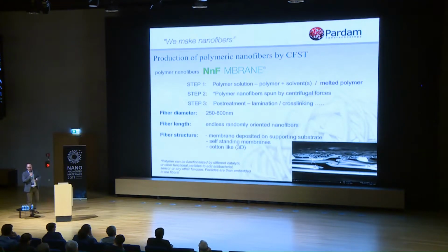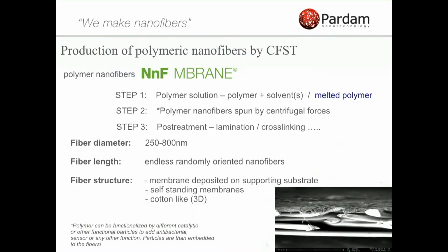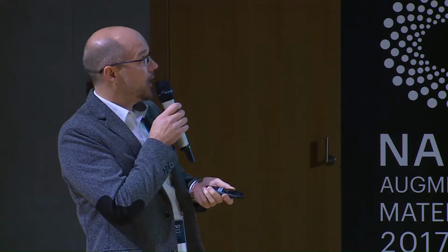It's a little bit easier to make polymeric nanofibers. You basically have, again, polymer solution, which you prepare by dissolving polymer in solvent or in combination of solvents, because the creation process for nanofibers is based on evaporation. So we sometimes combine 2 or 3 different solvents. Then we spin the nanofibers by centrifugal forces again. The main challenge for polymeric nanofiber membranes is its post-treatment, the lamination process, because the membranes are quite fragile, so you have to protect them.